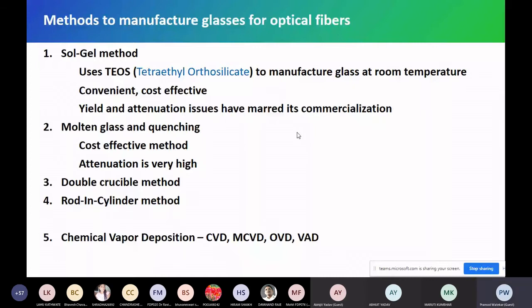So yield is very low. Most things have to be thrown out. In the lab, we use those parts for qualification or characterization. That's a different thing. But to get yield from sol gel is very difficult. We can get 15%, 20%, 30%. And that's why it's very costly also, and it takes a long time. We have to give sufficient time for the sol gel method to give the glass that we need. People are still using sol gel to make tubes, but we don't adopt it. It takes a long time, and then we cannot compete with our competitors.